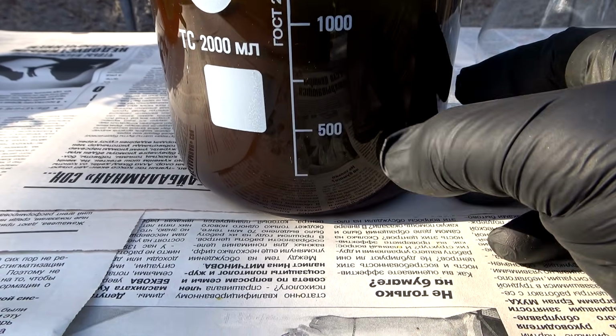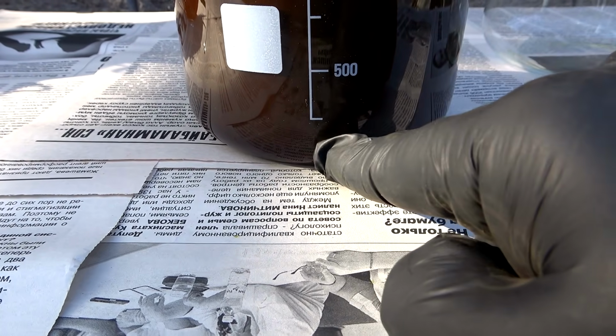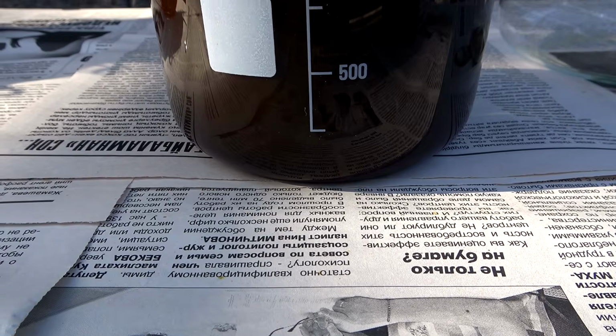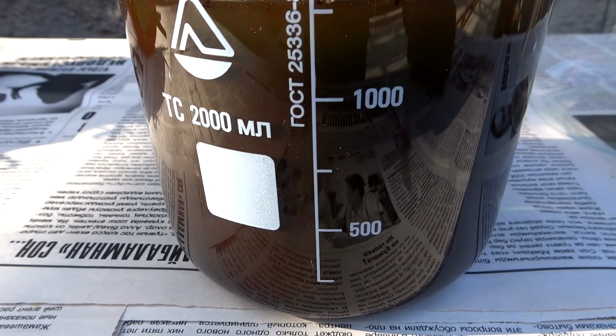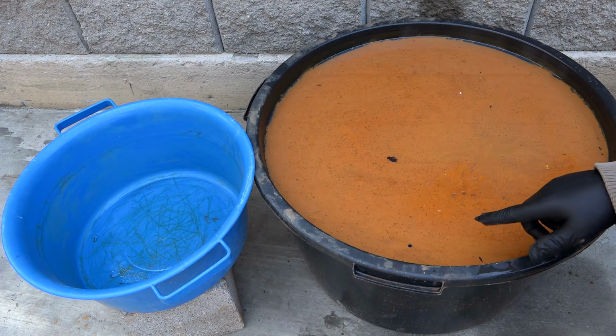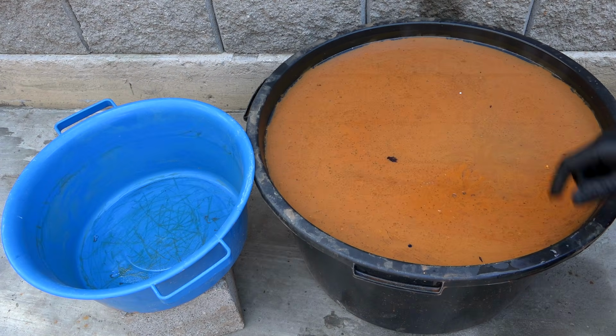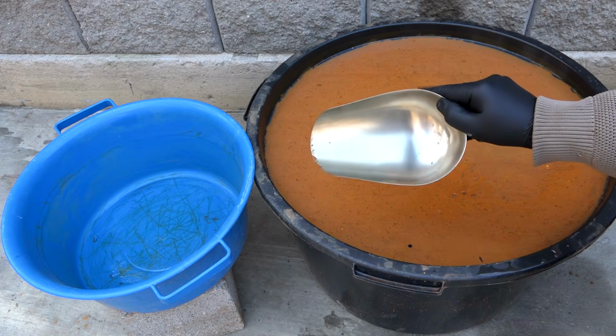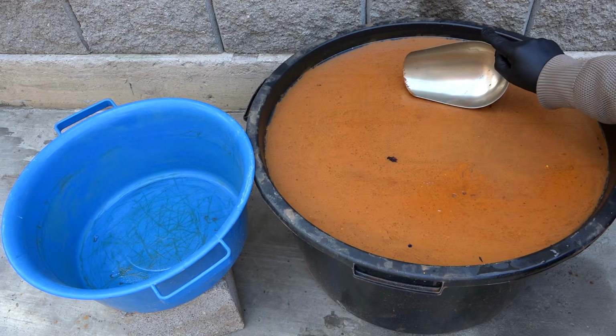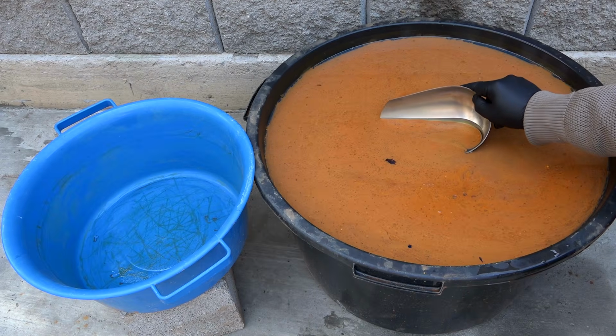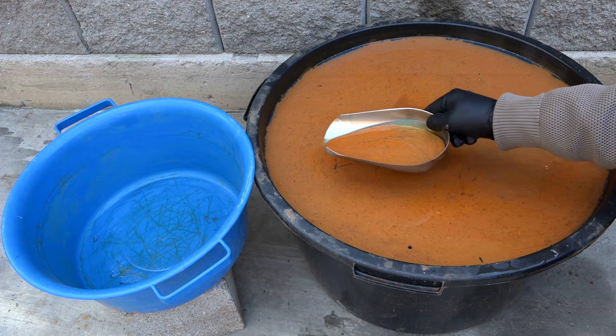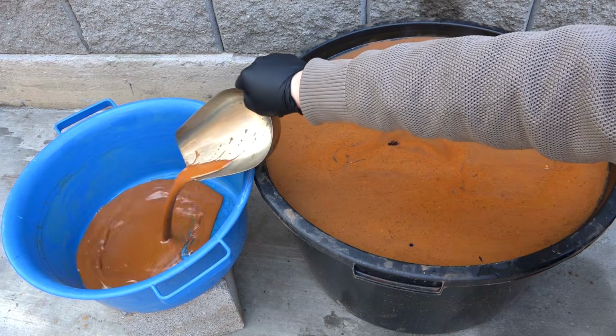Meanwhile, the gold sediment in the chemistry beaker has already begun to coagulate. An hour has passed, and now I'll remove the flotation foam. This can be done with a regular ladle. This foam can contain between 1 and 10% gold, and the maximum recovery from the pulp this way reaches 98 to 99%.